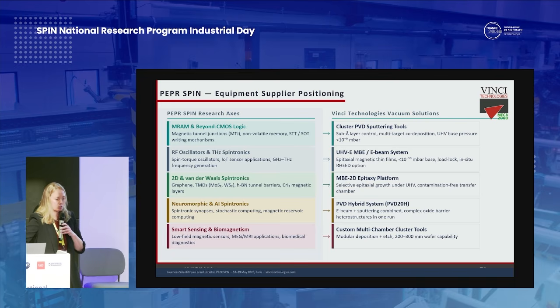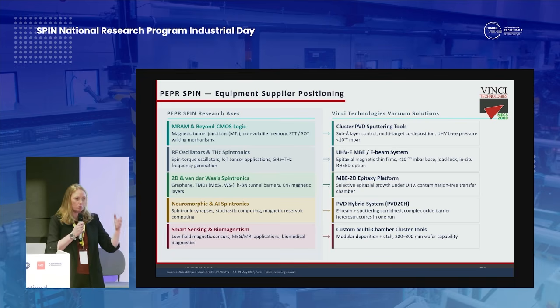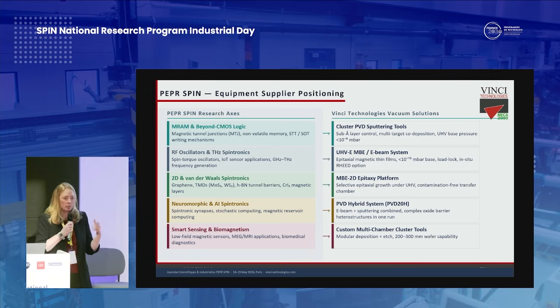The idea is to do scalable solutions. I won't go into this very much in depth, but it is to draw the link between the projects that exist, that we've talked about earlier today, and what kind of systems you can combine in order to achieve this. So by using sputtering systems for sub-angstrom layer growth, and very importantly using ultra-high vacuum systems for the growth of multi-target and co-deposition. For this purpose, we have systems with up to 8 magnetrons, so you don't have to break vacuum and change your materials.